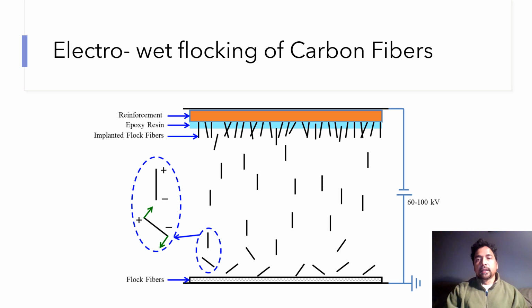The important process we employed is to reinforce short carbon fibers. In this study, we use two different kinds of carbon fibers. One is 150 microns, and the other is 350 microns long. They are around 7 microns in diameter. They were reinforced normal to the jute fabric using a wet flocking technique, where you have two conductive plates. These two plates are separated at a far distance, and on the bottom plate we spread carbon fibers evenly, and then we apply a high voltage of 60 to 100 kilovolts between these two plates. When it is applied, all these carbon fibers go and attach to the jute fabric, where you have a tiny layer of epoxy previously made with CNTs, so that the carbon fibers get stuck there and do not fall down.